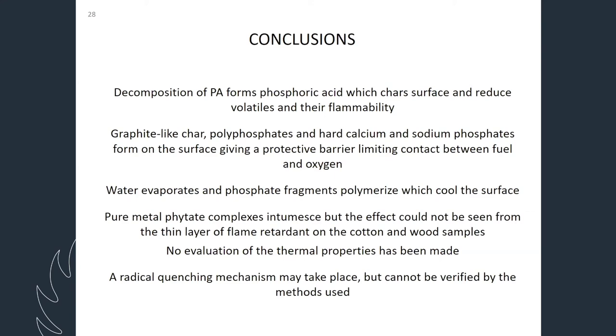We see that the phytic acid decomposes, gets phosphoric acid which chars the surface, reducing the volatiles and their flammability. We can see that the graphite-like char is formed. We can see that it polymerizes into polyphosphates, and we can see that it forms very hard ceramic-like calcium and sodium phosphates on the surface. So those will work as a protective barrier then, preventing the contact with the air.